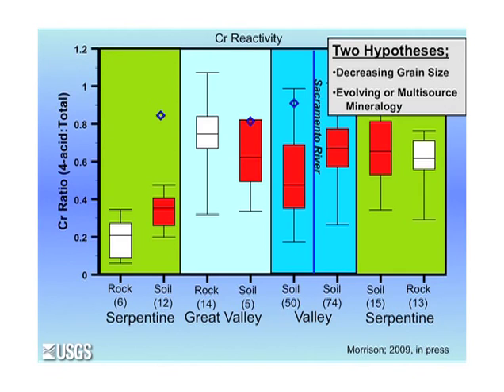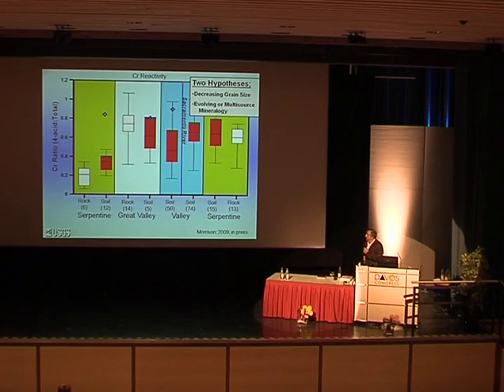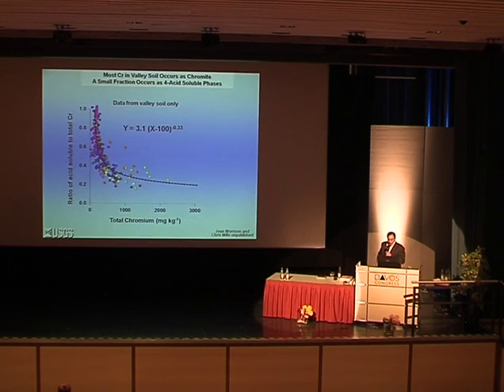So we've been working on a couple of different hypotheses. One is that during transport from the source area to the valley floor, the grain size of the chromite decreases and the solubility of the chromite is proportional to the grain size, increasing with decreasing grain size. And the other is that during transport, the mineralogy has changed from chromite to some other phase.